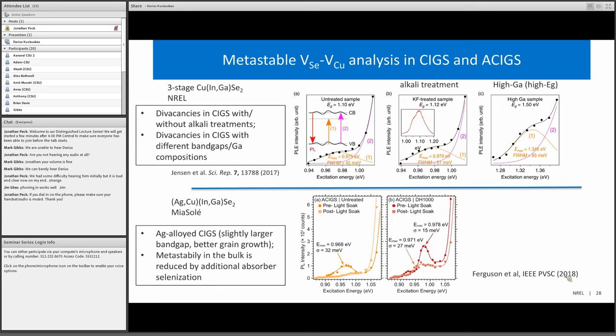But these metastable states are there, and because we can measure them and we can assign them to selenium and copper vacancies, the selenization of the absorber film allows the CIGS material scientists to reduce and to control this metastable defect density. So it was a very nice result to be able to provide these kinds of metrology tests done in non-destructive, contactless, and in some cases, rapid measurements.